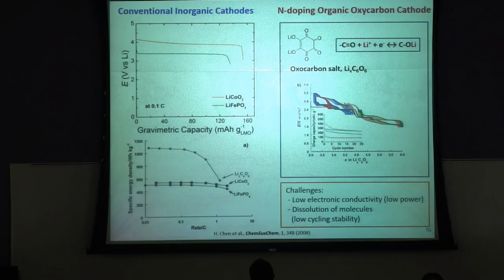So then, if I introduce n-doping type oxocarbon cathodes, let me first compare with the conventional inorganic cathode. This is lithium cobalt oxide and lithium iron phosphate, a conventional cathode material for lithium-ion batteries. As you can see, this kind of inorganic material has a capacity around 150 to 160 milliampere hours per gram. Their redox potential is around 3.5 to 4 volts.